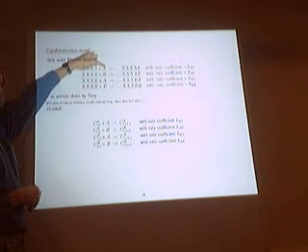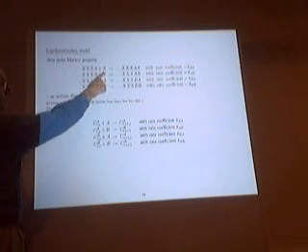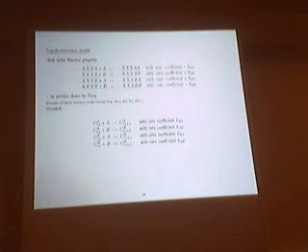So we have a polymer that ends in A, adds to another monomer that is A, and gives you another polymer that's the same as this one, that's got two A's on the end, and that's going to happen with this rate coefficient KAA. A polymer that ends in A could have B added to it, and that happens at some rate KAB, and similarly for polymers that end in B and added to A and B ending in B.